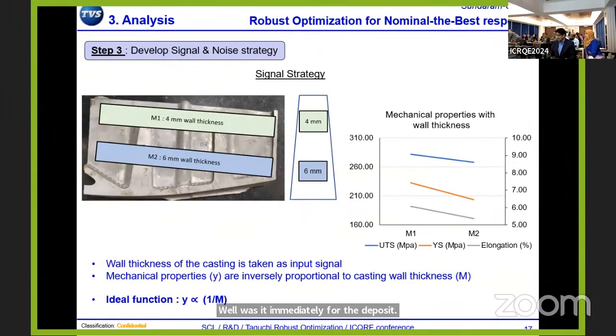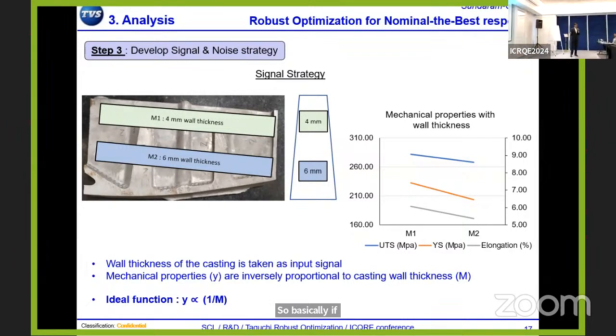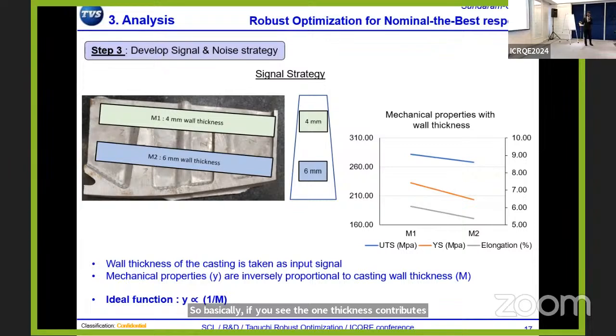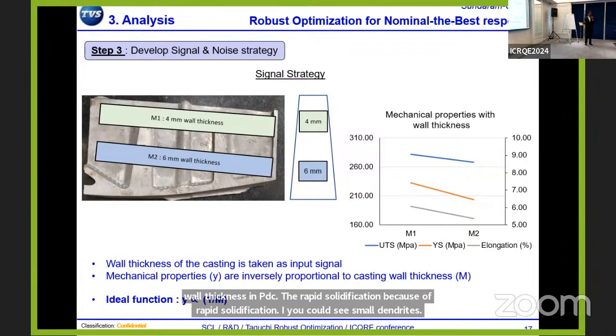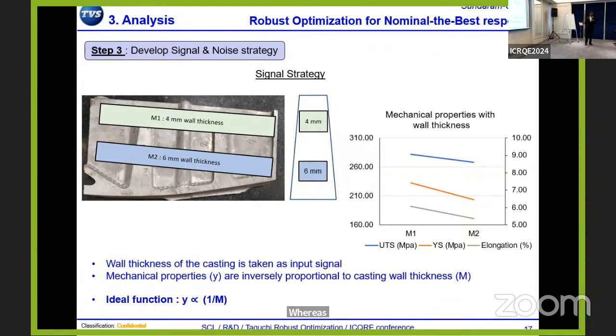So basically, the wall thickness contributes to the mechanical properties. If you have less wall thickness in PDC, because of rapid solidification you could see small dendrites. Whereas if you go for high wall thickness, the dendrite size will be somewhat bigger. The mechanical properties of a component normally depend on the dendrite size. It is directly proportional to the dendrite size. So if you have very small dendrites, you will get higher mechanical properties. If you have large dendrites, you will have lower mechanical properties. Large dendrites will reduce the strength, yes.